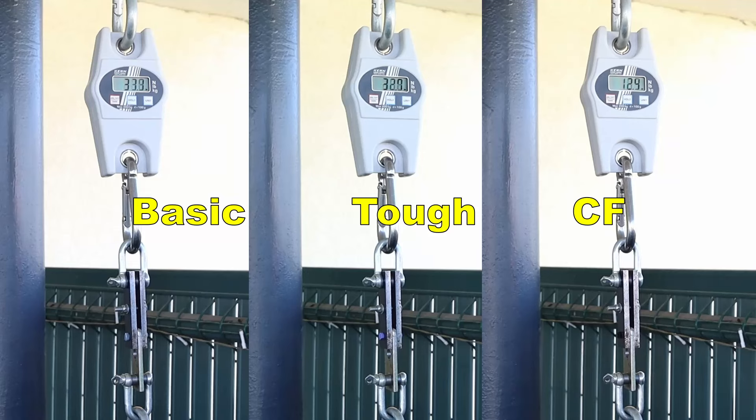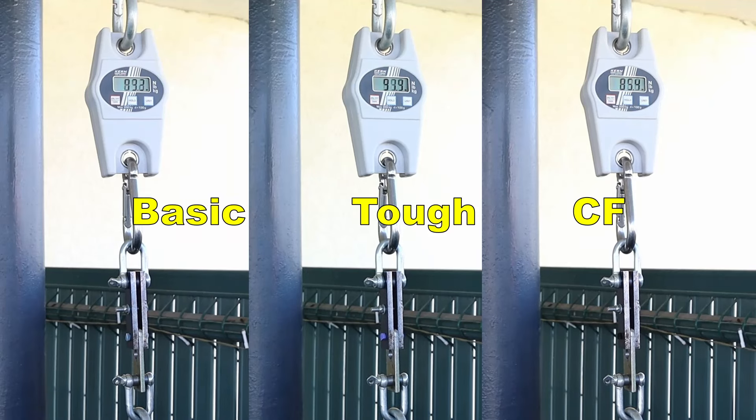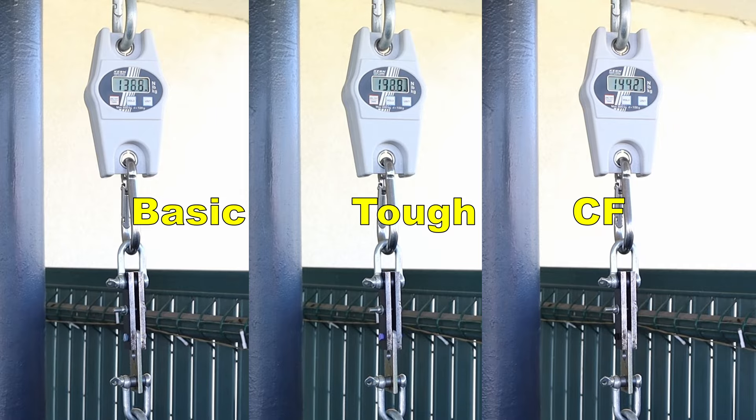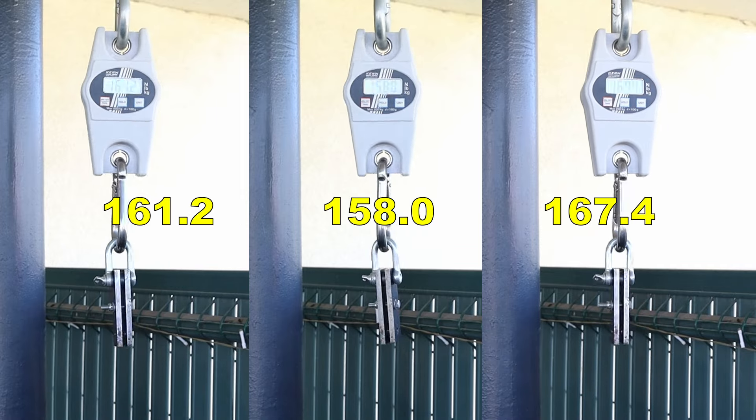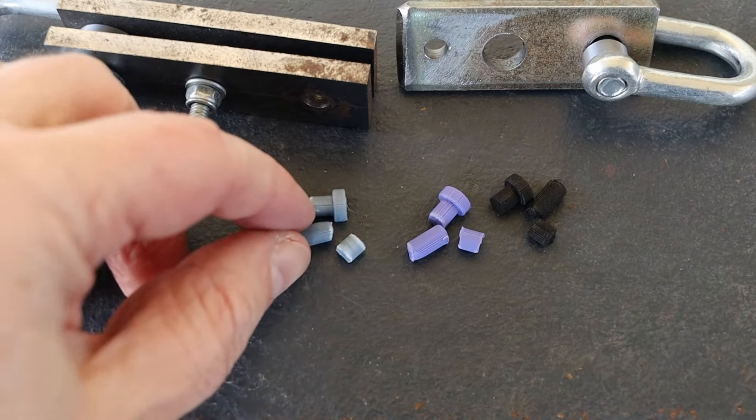Two-sided shear stress. The numbers are similar but the carbon fiber was a little bit stronger because the orientation of those fibers really helps in this kind of stress.